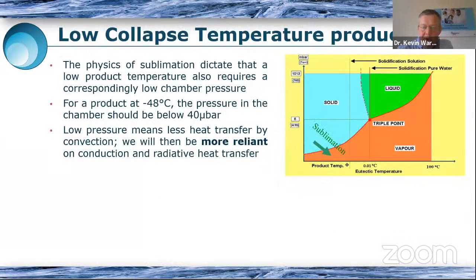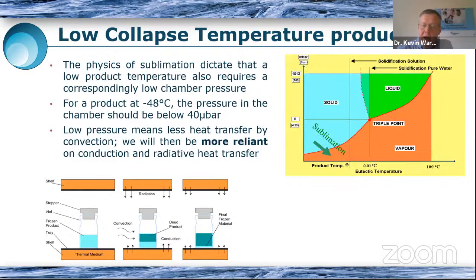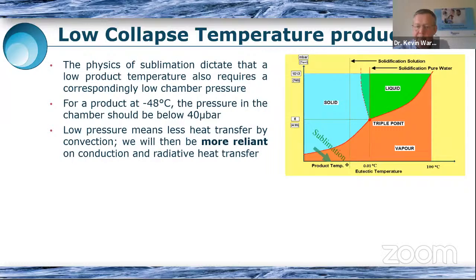And so just to finish off by talking about some of the challenges of the freeze drying process, we know that what we've often encountered for diagnostics is that they often have very low collapse temperatures. And looking at our phase diagram here, we can see that sublimation has to happen. If we want to go directly from solid to vapor, we're talking about relatively low temperatures. But what we also then have to do is to adopt very low pressures. So the laws of physics tell us that if we've got a very low temperature, then in freeze drying we have to use a correspondingly low pressure. So the pressure will be related to this line here that divides the solid and the vapor states. So if we're just below 0 degrees, then probably anything just below 6 millibar will be fine.